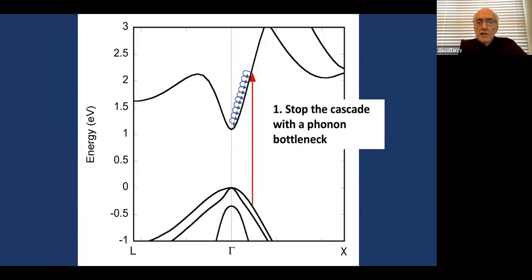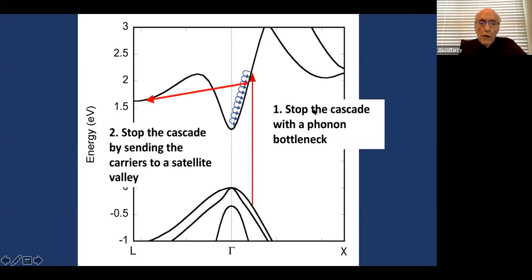Now, the first step is you want to stop this cascade from rattling down here, right? You need to stop that with some type of phonon bottleneck. That's the first thing that they proposed. Now, we suggested about a year ago, rather than using a bottleneck, the electrons that are sitting up here want to transfer over here to the satellite valleys. These are metastable valleys. And the electrons will stay there for several picoseconds. And in several picoseconds, these electrons can travel a micron. So you can get them out of the device without them ever going back to the central valley of the conduction band. So we send them to a satellite valley.